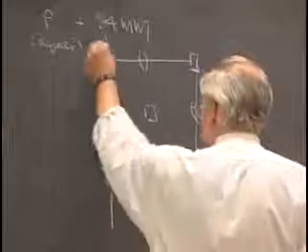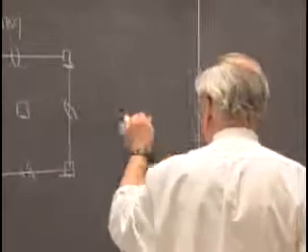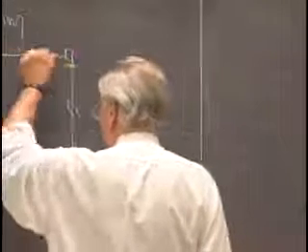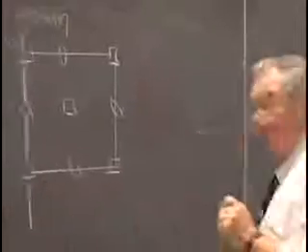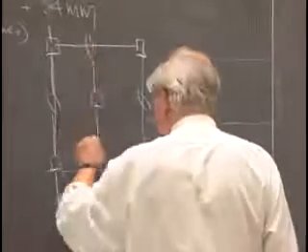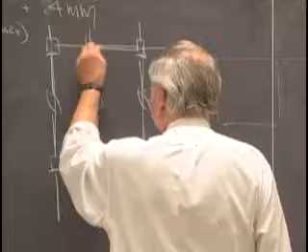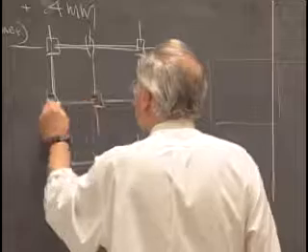And then 4mm has one kind of mirror plane, 2mm because there are two kinds of mirror planes. The mirror plane says, hey, if I'm in a lattice, I want to be at right angles to a rectangular or a centered rectangular net. Well, okay, this one is happy because a square net is a special case of a rectangular net. The two translations are merely equal. So he is happy. Combine that with T2, and we'll get another mirror plane like this and another mirror plane like this. Fourfold axis is going to rotate that mirror plane, so we'll have mirror planes running this way and this way as well.